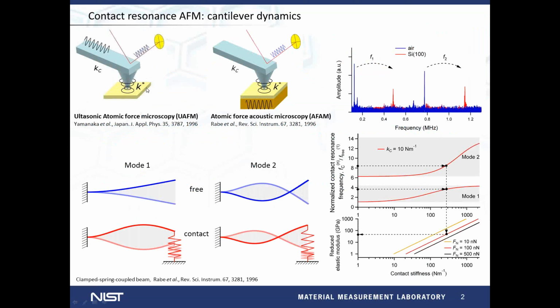Briefly, in contact resonance AFM, an AFM tip is brought into contact with a surface at a given applied force, and while in contact, it is mechanically vibrated by a small amplitude oscillation at one of the eigenmode frequencies of the cantilever-tip-sample system. Here we are showing the two most common configurations. One is with modulation applied at the end of the cantilever by the piezo shaker of the AFM, and this configuration was introduced by Yamanaka and Nakano as ultrasonic atomic force microscopy in 1996. The other one is with modulation applied underneath the sample and was introduced by Rabe, Jenser, and Arnold as atomic force acoustic microscopy, also in 1996.